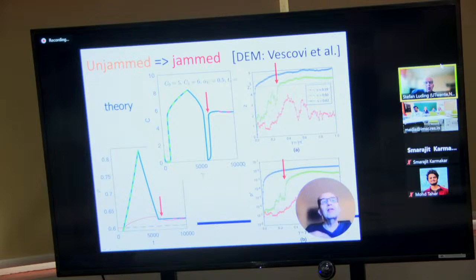Now, there is a special case, and that is when you have an unjammed system and you shear and the system jams, as was presented by particle simulations by Vescovi et al. a few years ago, and we made the theory for this, which gives density and coordination number and pressure, all the continuum quantities, and the red arrow indicates the jamming event. So there is a possibility that you have an unjammed system, you shear, and you jam the system. In simulations, it's the green line. In theory, it's the blue line with the marker.